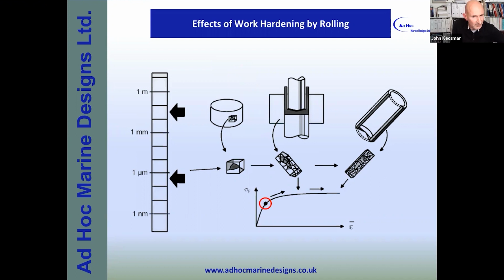If we assume the little black dot there is O temper as you're starting to roll it, bend it, and form it as shell plating, it's going to slowly go around the stress strain curve to approximately somewhere around about here. Whereas the H321 probably starts approximately in that location. And then as it's rolled, goes up to much higher on the curve. So you can see, even though the grain structure is actually decreasing and increasing in strength, you're reducing that ductility and also getting closer and closer to possible failure.